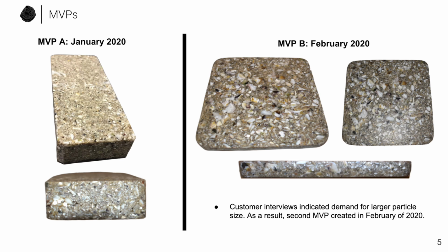From this feedback, we created our second MVP in February, as seen on the right, with a much larger particle size distribution range. This second MVP consisted of, again, roughly 30% resin by weight and particle size distribution ranging from 1 micrometer to 20 millimeters, with a final density of roughly 2.3 grams per cubic centimeter. This was the last MVP we were able to make due to the closure of UBC campus. In summary, these MVPs proved the technology of Stone Oyster and allowed potential customers to imagine a full-scale countertop.